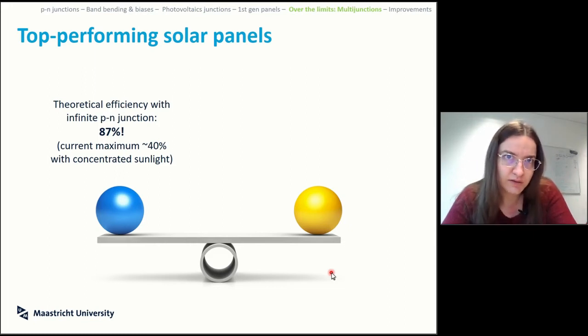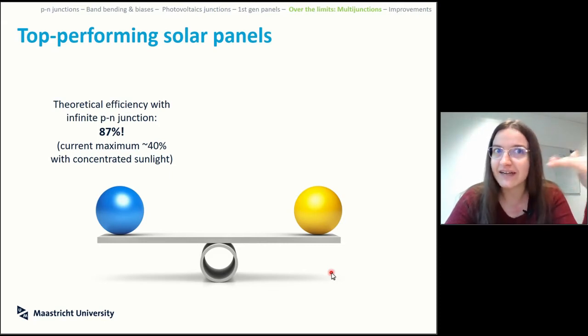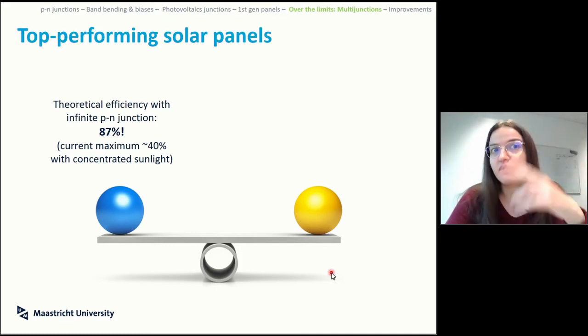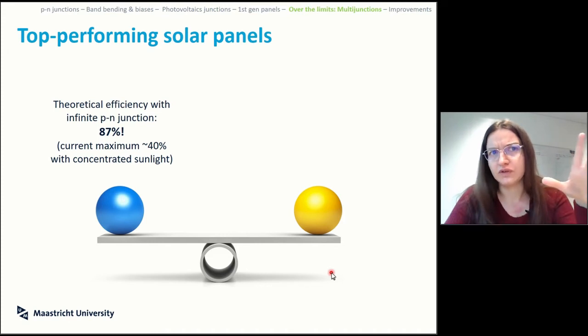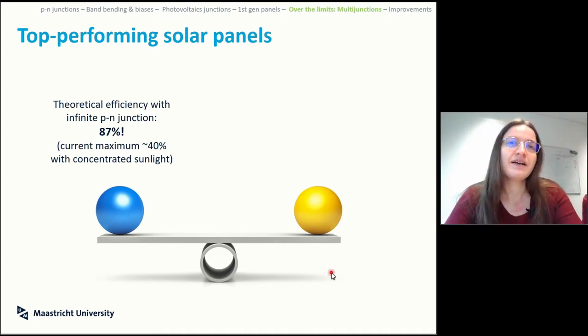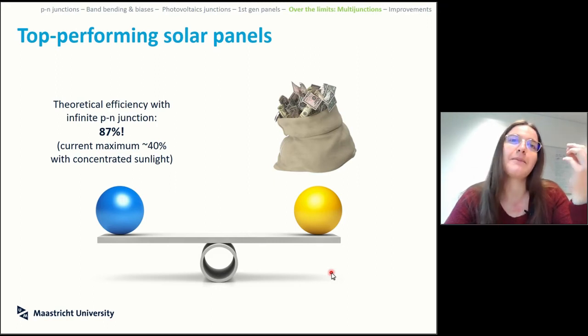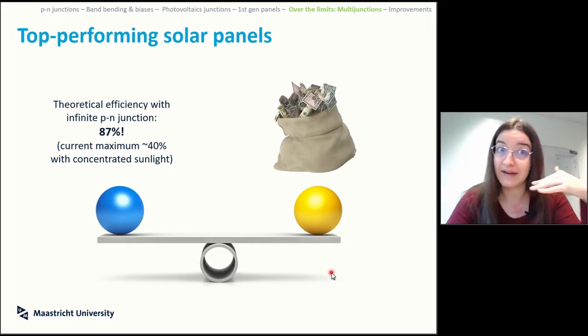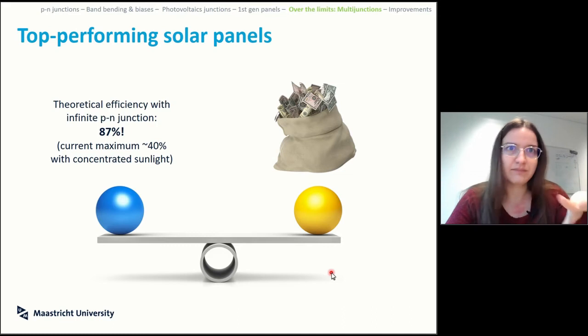This is huge. But 87 requires a sequence of layering, and the more stuff you want to layer, the more challenging it becomes to have the tunnel junctions, to have actual transmission of light that doesn't get absorbed. So the current efficiency of solar cells is actually a bit above 40%, but not 80, certainly. And you can already guess what the problem here is, that this thing is incredibly pricey. These are not like silicon monocrystalline single cells. These take a lot of money. Bringing them up, layering them up, making sure that the connections are nice and steady is difficult. The materials to begin with are pricier than what you will have with silicon single crystal.